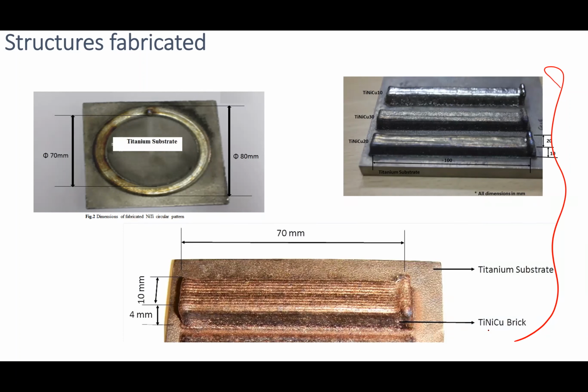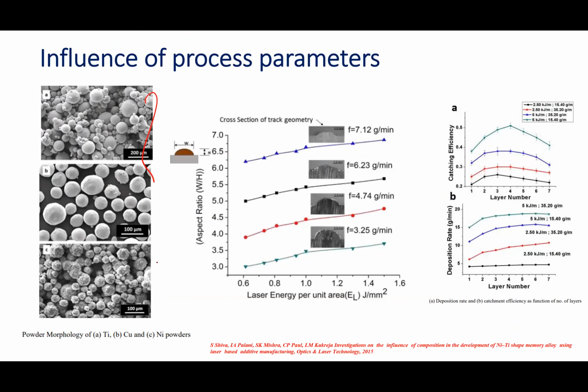Now, since we are using a powder, our main motto is to investigate the influence of process parameters. One of the key parameters is the particle size which is chosen. The Ni and Cu powders had a particle size within the range of 45 to 106 micrometer, whereas the range is 75 to 150 micrometer for titanium. These ranges of powder particles were selected for the experiments. Particles with a bigger size and wider range result in semi-fused particles due to a smaller absorbed laser energy per unit mass.